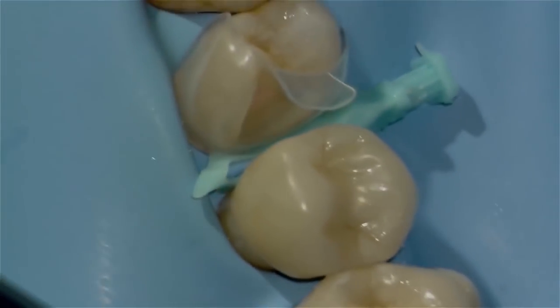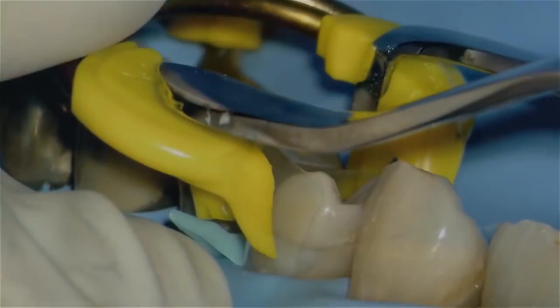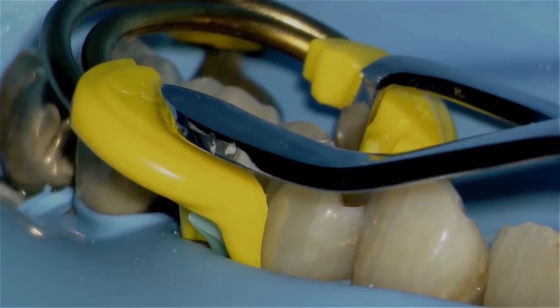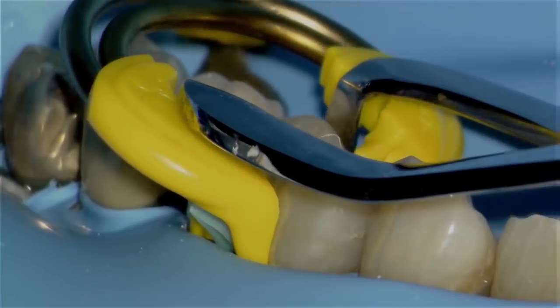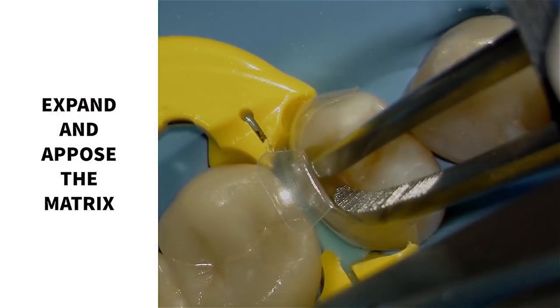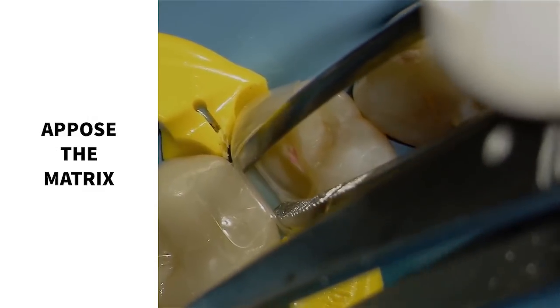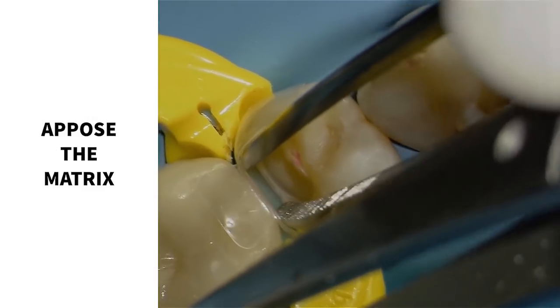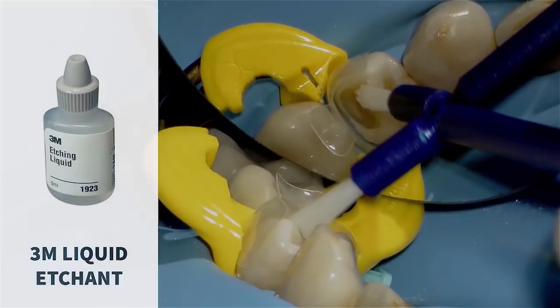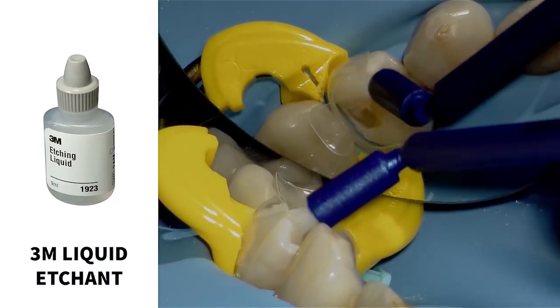Now, in this particular case, the matrix looks like it's going to be a problem, but once I get the separator on here and I walk the matrix over, I'm going to expand and appose the matrix. It's laying so beautifully against the neighboring contact, and I think it's because my line angles were maintained. I don't have to do that spot weld technique.